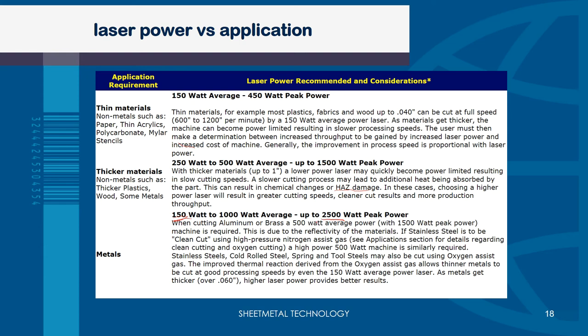And for metals, you can go from 150 watt up until 2500 watt power. This is what we use to cut aluminium or brass, due to the reflectivity of the materials. If stainless steel is to be clean cut using a high pressure nitrogen gas, then you should use a high power 500 watt machine. Cold rolled steel and spring tool steel can also be cut using an oxygen assist gas.